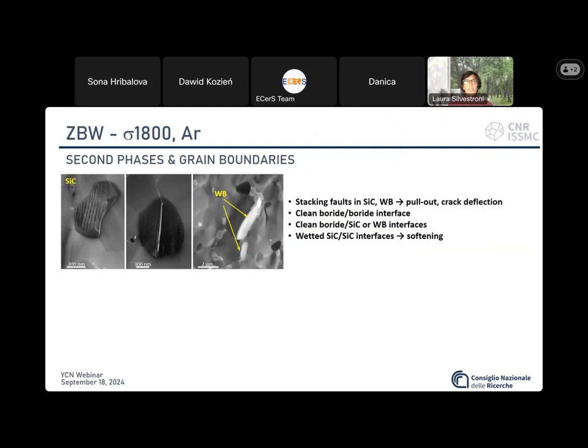Then I checked the second phases, and both silicon carbide and tungsten boride displayed stacking faults, which are beneficial for crack deflection. If you look at these silicon carbide particles, you can see that when the crack crosses the line defects, crack deviation occurs, whereas when the crack meets the defect along its longitudinal direction, it proceeds straight without any deflection.